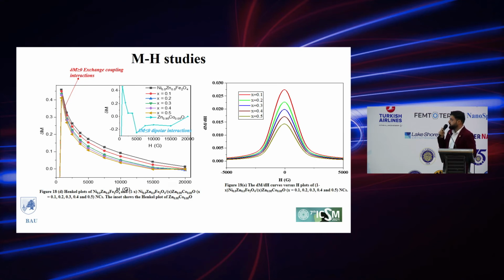Finally, switching field distribution was done for all samples by plotting the dM/dH versus H curves. All samples have shown a single peak, confirming the presence of a single magnetic phase, and as you can see, with the amount of the zinc cobalt oxide in the nanocomposite increasing, the full width at half maximum and the intensity decrease, again signifying the deterioration of the exchange coupling between the two phases.